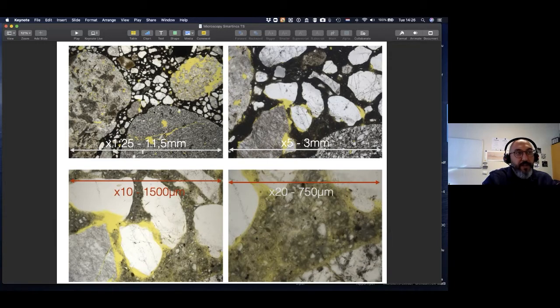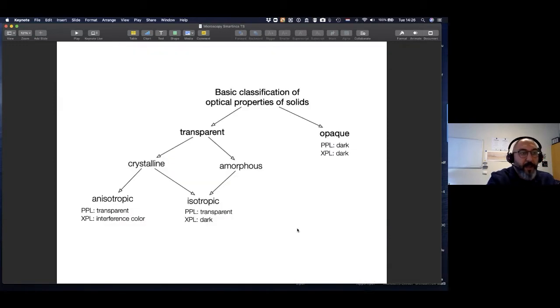You see this upper left-hand side is a low magnification, because you can easily understand by looking at the field of view, which is from left-hand side to right-hand side of this image. It's 11.5 millimeters. It's quite large. But you can change your objectives from 5 to 20 to whatever you have in order to have the details of your microstructure. So that's the beauty of microscopy. Actually, you don't need to only look at a single magnification, but you can zoom in and zoom out and go to different spots to understand your material even better.